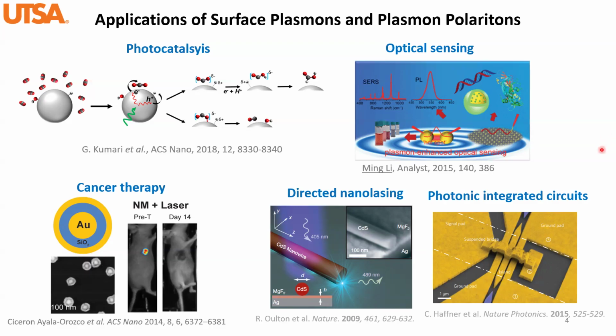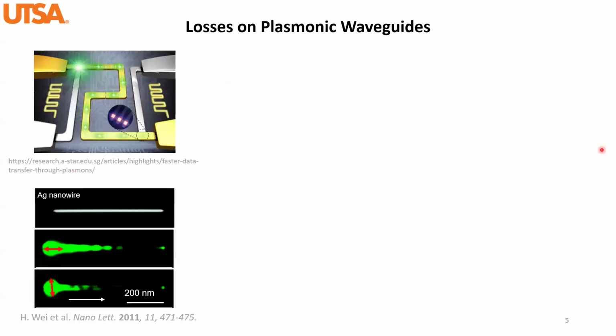So in terms of plasmonic waveguides, of course, there is actually a big problem hidden behind it, and that is the losses. We have been using silver nanowire as a very typical plasmonic waveguide, and it is the most well-studied plasmonic waveguide. Say, for example, if you couple light into this end, you're expecting the surface plasmon to propagate along the silver nanowire and eventually have the light coming out.